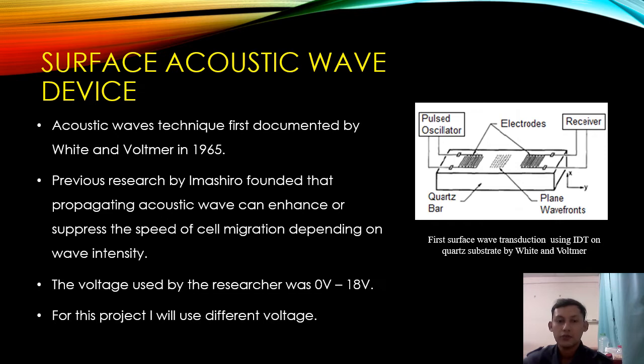Surface acoustic wave device. The acoustic wave technique was first documented by White and Voltmer with the introduction of the IDT in 1965. They showed that the IDT, which consists of periodic thin film metal electrodes over a quartz substrate, can generate a frequency traveling across the surface as an acoustic wave.